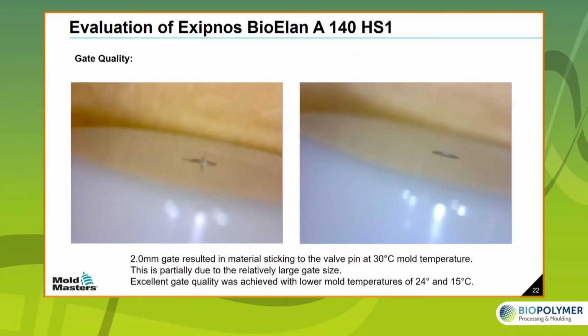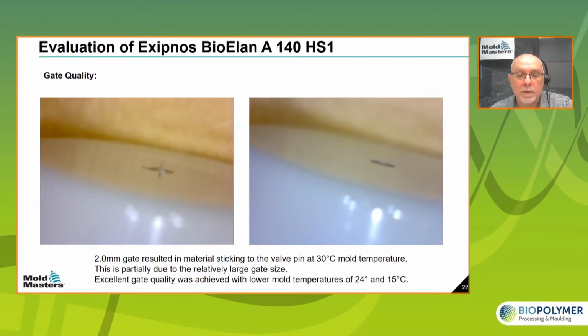Here we see the gate appearance that resulted with our valve-gated system. On the left-hand side, we can see that there is some gate vestige. This is not desirable. This was happening with the 30 degree mold temperature. This is partially due to the larger gate size. This is a relatively large gate on a closure, 2 millimeters.